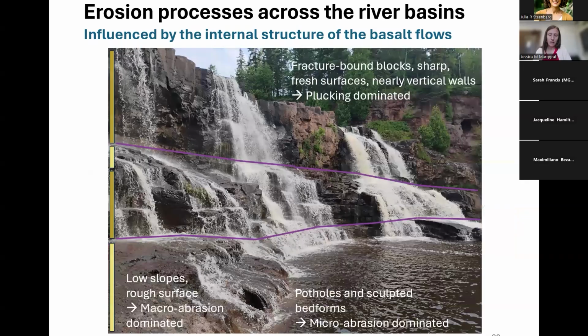observation from our river. Here is an example from the falls, from Gooseberry River. Here we can clearly see three different basalt flows: one here at the top, the central one, and then the lower one down here. And we can also relate it to the different erosion processes like abrasion, impact erosion, and plucking. So in the top part, we can see these very sharp surfaces, the nearly vertical walls, which are also corresponding to the cooling fractures of the basalt flow and these columns.